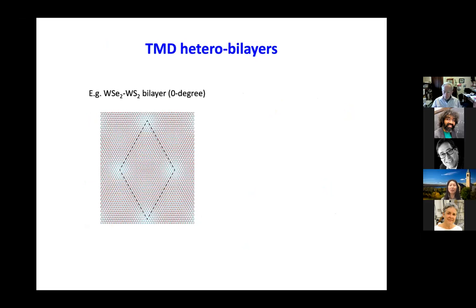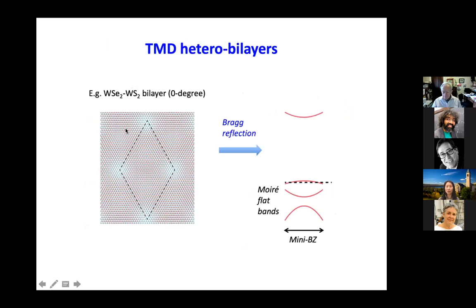So now we introduce this long wavelength period. In this case, we introduce Moiré potential by stacking it on top of another similar material with slight lattice constant difference. And then you have this triangular lattice with a period of 8 nanometers. So now if you put electrons, there will be extra Bragg reflection because of this superlattice period. So the single band I showed you, for example at the K point, now will be folded, right? And that will give us many mini bands.